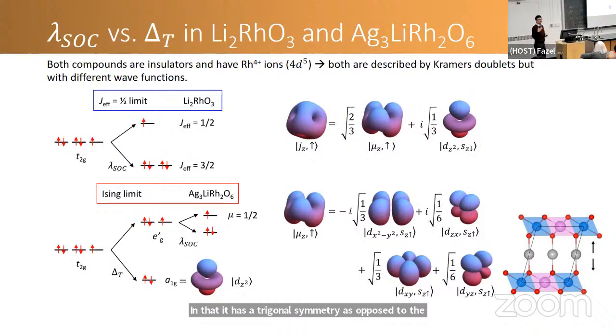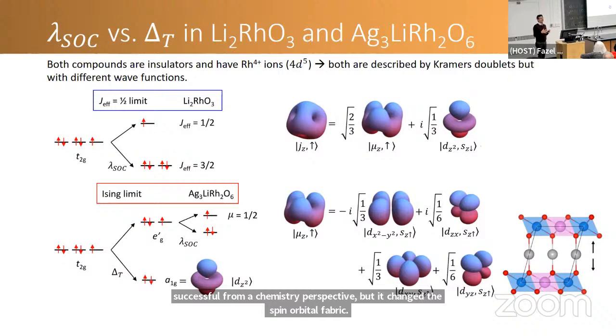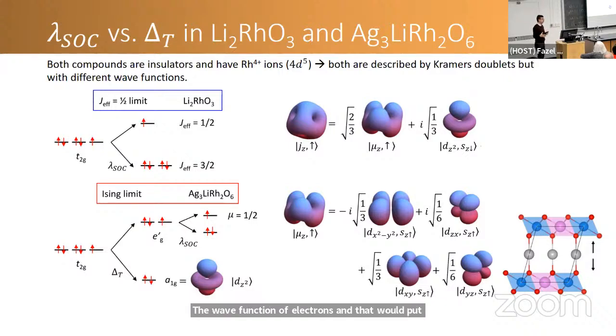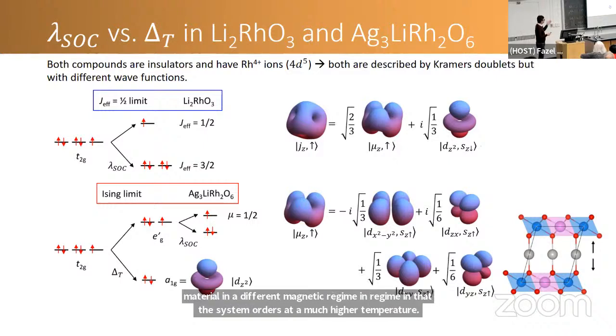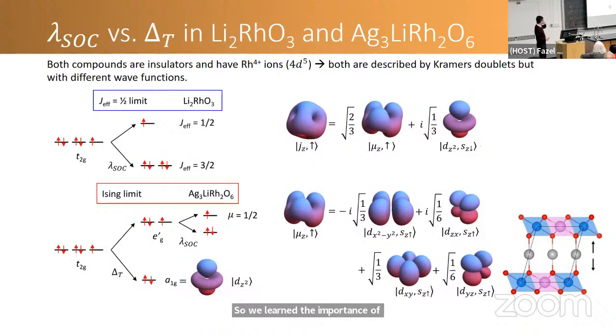And therefore, our exchange reaction, although it was successful from a chemistry perspective, changed the spin orbital fabric of the wave function of electrons, and that would put the material in a different magnetic regime, in that the system orders at a much higher temperature. So we learned the importance of trigonal compression.